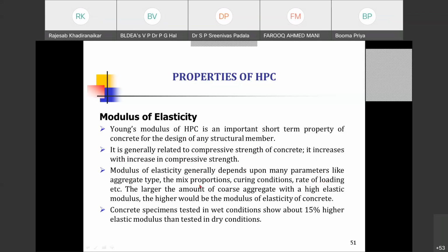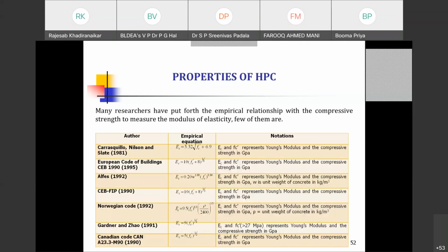It depends on parameters like aggregate type, mix proportions, curing conditions, and rate of loading also. The larger the amount of coarse aggregate, the higher would be the modulus of elasticity. And specimens tested in a wet condition indicated around 15% higher elastic modulus compared to dry conditions. That was basically because of the drying effect that takes place in concrete.